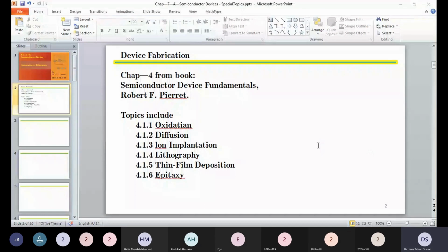Silicon is highly reactive, and a thin native oxide layer is rapidly produced by simply exposing silicon to the atmosphere at room temperature. Silicon oxide layers of controllable thickness are produced during device fabrication by reacting silicon with either oxygen gas or water vapor at a controlled temperature.